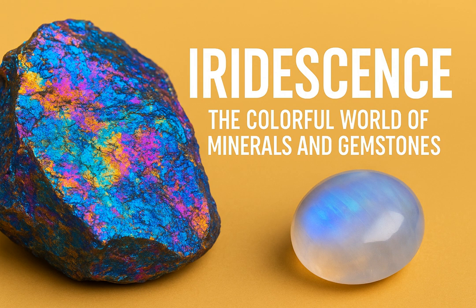Layer upon layer upon layer. So how does the orient, the iridescence, happen there? The orient of a pearl is created as light reflects from these thousands of regularly spaced microscopic layers of nacre, but it also diffracts from the even finer, regularly spaced crystal boundaries within those layers. So reflection and diffraction, both playing a role. This intricate layered structure creates the subtle, moving, almost ethereal colors we see, giving the pearl its characteristic soft glow and shifting hues.